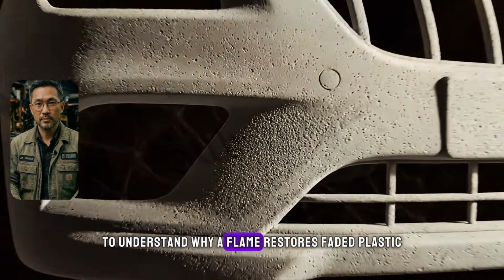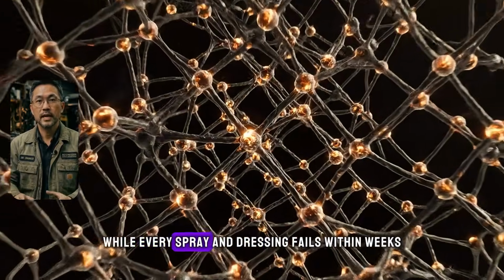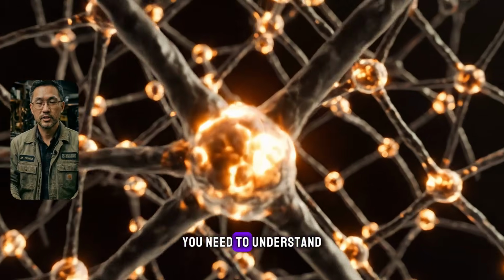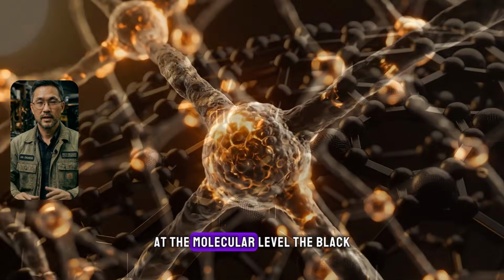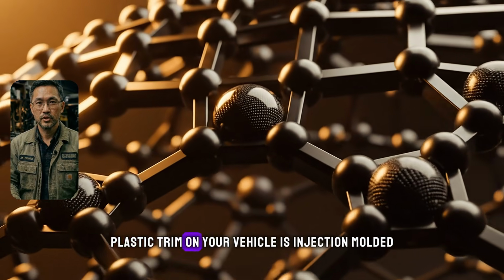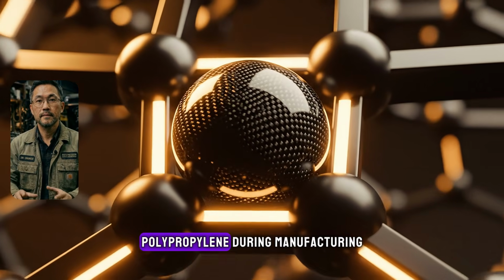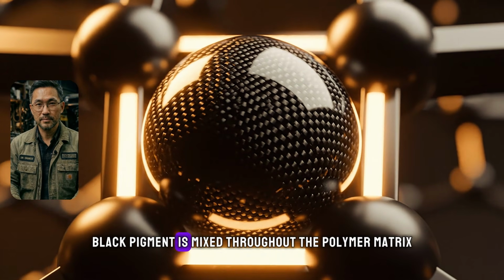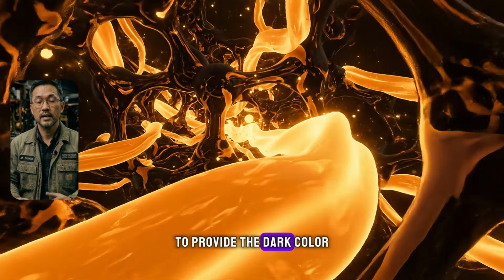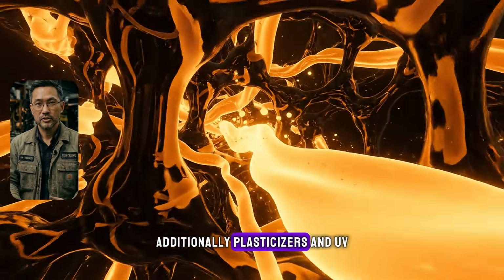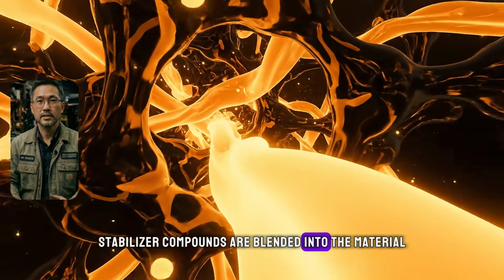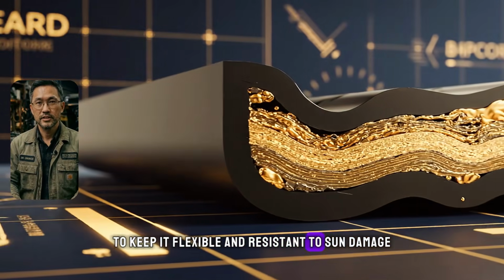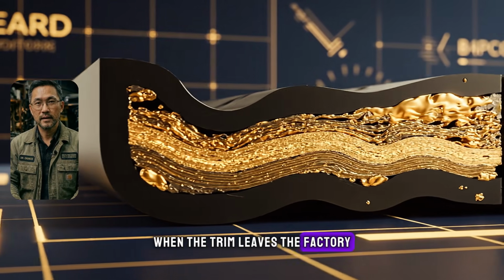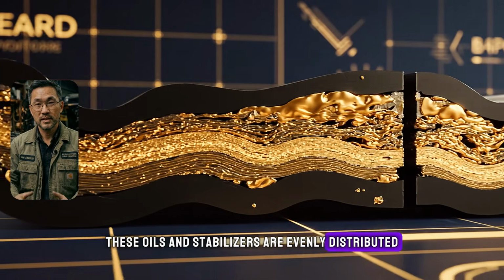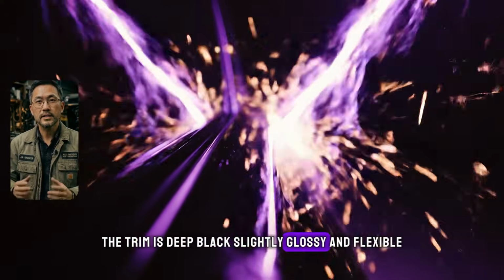To understand why a flame restores faded plastic permanently while every spray and dressing fails within weeks, you need to understand what is actually happening to the plastic at the molecular level. The black plastic trim on your vehicle is injection molded polypropylene. During manufacturing, carbon black pigment is mixed throughout the polymer matrix to provide the dark color. Additionally, plasticizers and UV stabilizer compounds are blended into the material to keep it flexible and resistant to sun damage. When the trim leaves the factory, these oils and stabilizers are evenly distributed throughout the plastic, including at the surface. The trim is deep black, slightly glossy and flexible.